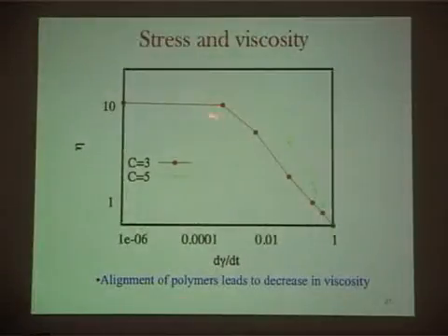Now this is the viscosity. You can see the green line. This is related to your question about what happens. If I look at the viscosity, this is for 5%, and you can see the viscosity diverges at zero shear rate. For this system, it's showing that that's actually a gel phase. Below that concentration, you see a plateau in the viscosity, and then it shear melts. Basically, it has shear thinning at some value of shear rate at which this layer starts forming.